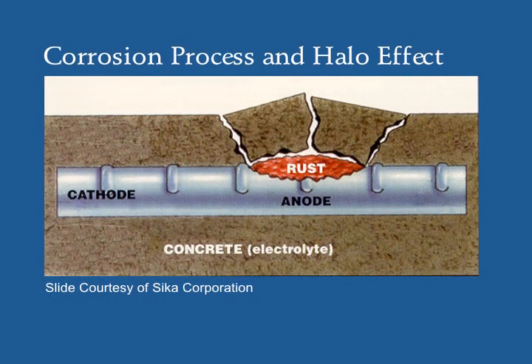This schematic, courtesy of the Sika Corporation, gives us a picture of the four components of the corrosion circuit, namely a cathode and anode and electrolytic path, which is provided by the pore water, and a metallic path, which is the steel itself. As chloride concentrations increase around the rebar compared to other locations, that location becomes the anode, and that's where the actual corrosion occurs. Because rust itself is 500 to 700% larger in volume than the parent material, it produces a bursting stress within the concrete.